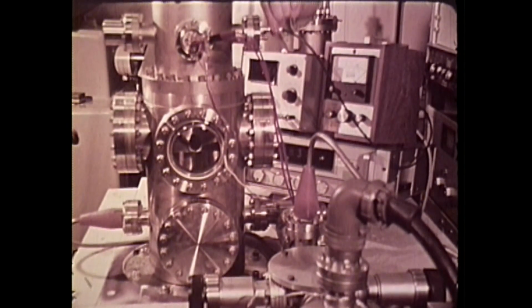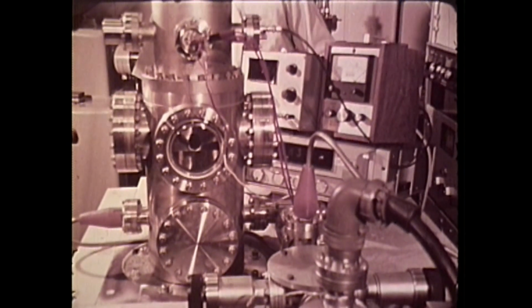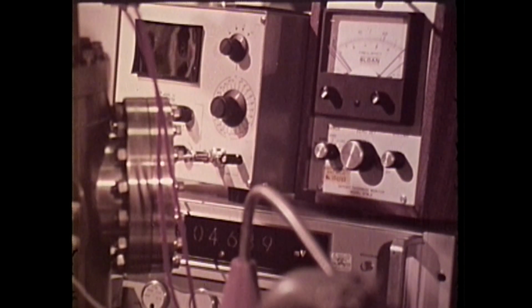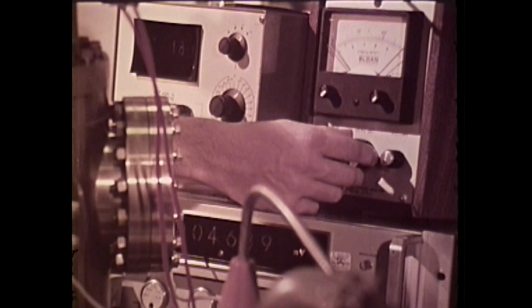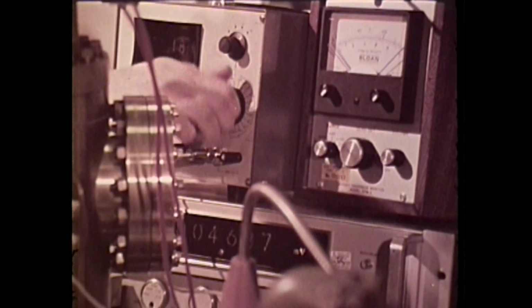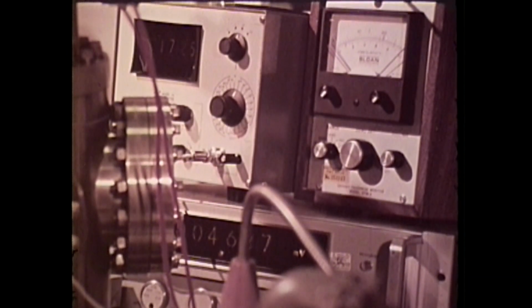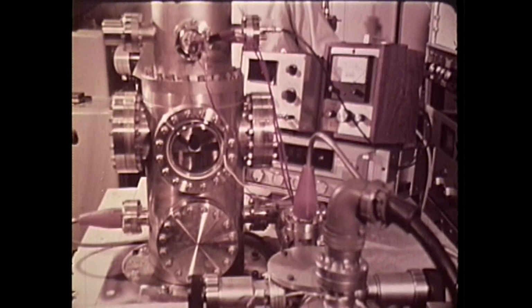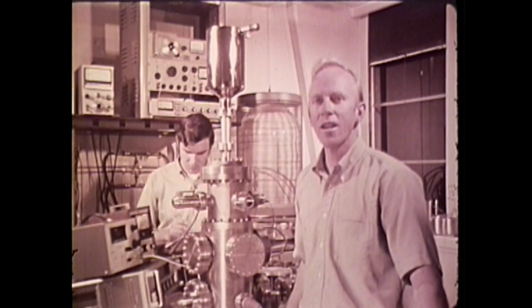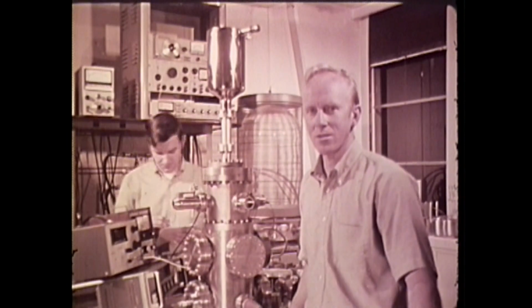We're depositing high-density, highly reproducible films in a vacuum on the order of 10 to the minus 9 torr. In order to avoid atmospheric contamination of our newly formed amorphous material, we do our testing in the same chamber where the film was formed. You know, there's been a lot of disagreement about amorphous semiconductors.